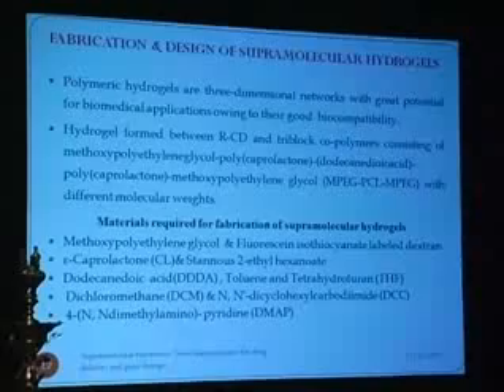So what is the fabrication or design of the supramolecular hydrogels? The polyethylene glycols, fluorescein isothiocyanate labeled dextrans, epsilon-caprolactone, stannous 2-ethylhexanoate, dodecanedioic acid, toluene, tetrahydrofuran, dichloromethane, N,N-dicyclohexylcarbodiimide, 4-N,N-dimethylaminopyridine. So these are the basic requirements. Whenever you are designing supramolecular polymers, you have to use these materials. Thereafter, you prepare a suitable concentration of the polymer. Then you go for incubation along with continuous stirring. You will get supramolecules. But you have to characterize whether it is within the range of 10 to 30 nanometers or not. So these are the basic gel compositions to prepare supramolecular hydrogels.